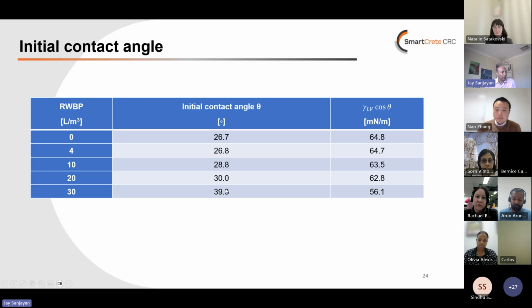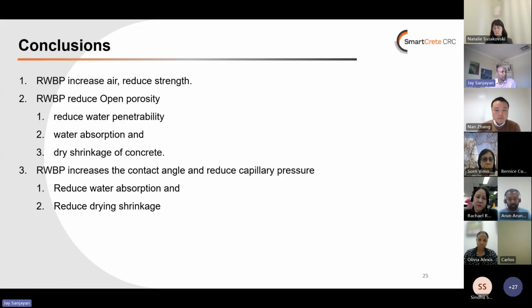because as the angle increases, this factor decreases, because that's the cosine of the angle. So that means the capillary pressure decreases. So in conclusion, we can say that the water-based paint increases air, which leads to a reduction in strength. Open porosity reduces with increasing paint, which subsequently reduces water penetration, water absorption and drying shrinkage, and also increases the contact angle, which has an effect on water absorption and drying shrinkage.